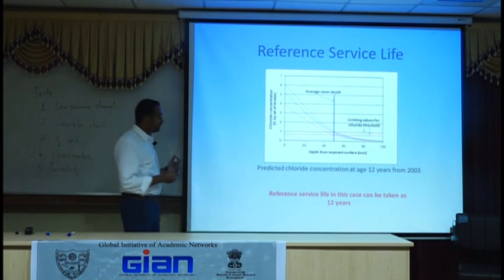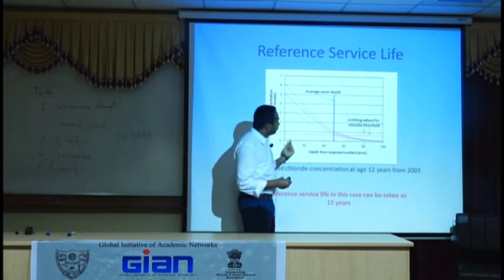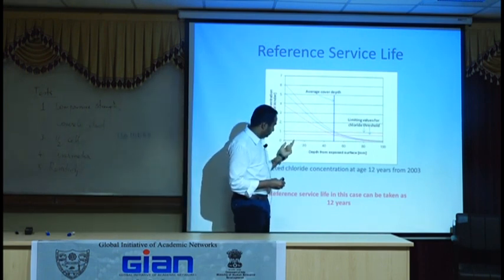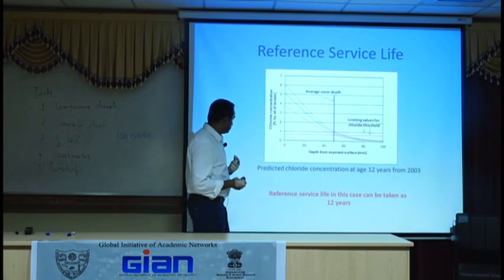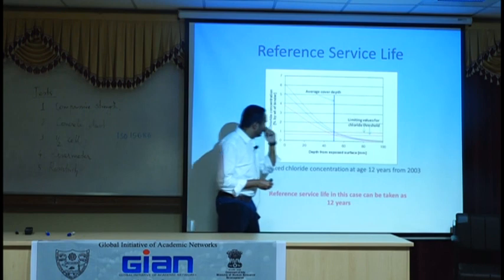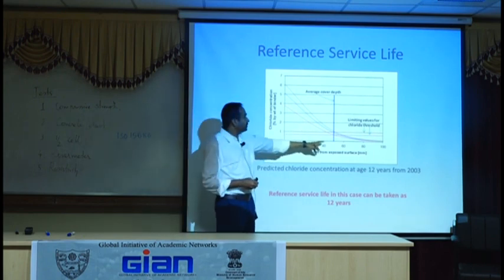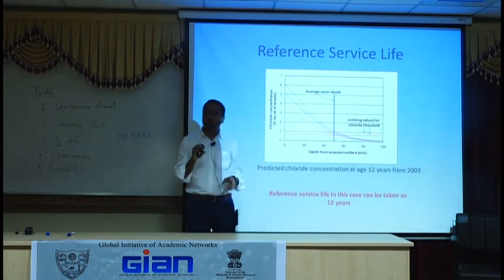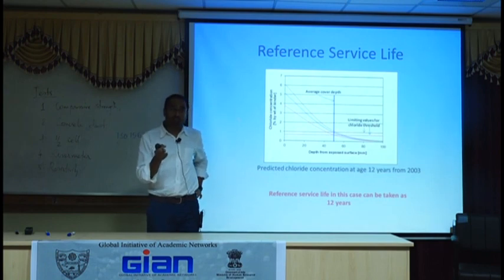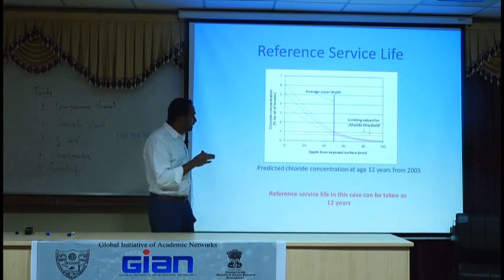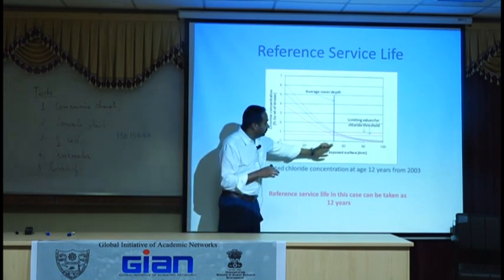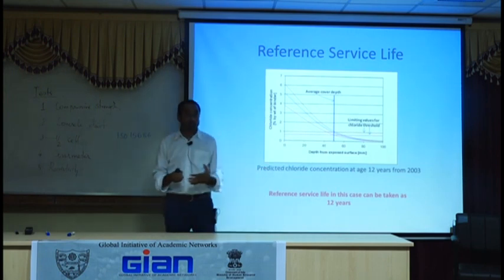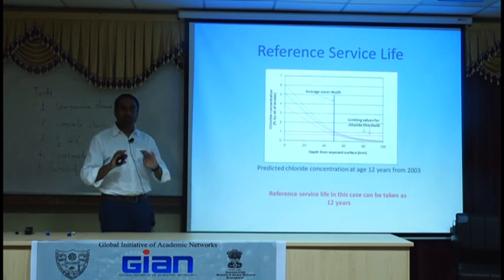So, reference service life in this case, if I move the average cover depth to be 50, but I don't know if 50 was what they prescribed and 35 is what they achieved. I'm not sure what happened in between. If the average cover depth was to be 50, then I get 12 years before corrosion starts. That is your reference life.